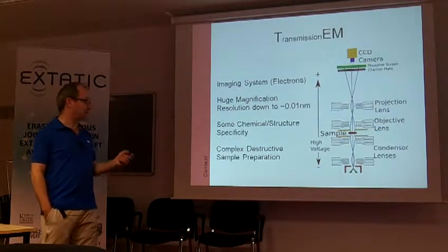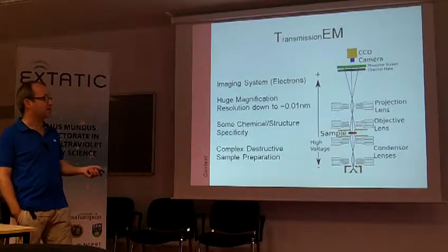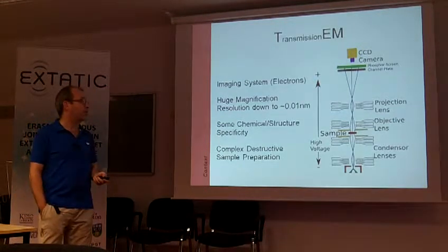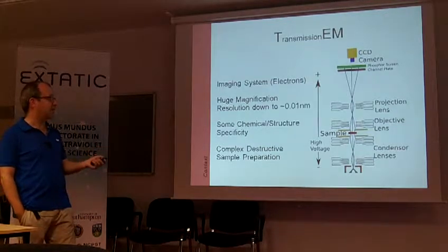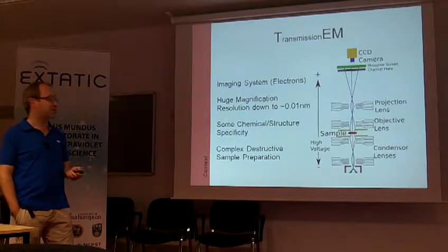Moving on to imaging techniques, if you look at transmission electron microscopy, it again takes a source of electrons, but this time it uses that source of electrons to illuminate an object field on your sample. And the transmission of this electron illumination through your sample is what gives you your image, through an objective and projection lenses in the transmission electron microscope. And the resolution from TEMs can be enormous, but the disadvantage for somebody trying to image is that you have to have an extremely thin sample, and that sample has to have high contrast.